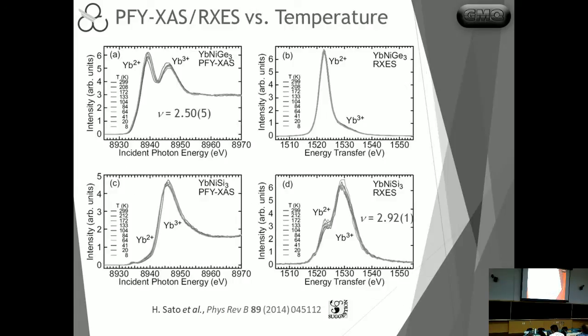An interesting thing, which I think was actually the first time that they could show this very well, was that for different systems you do get different types of responses. And so different techniques can be applied to different systems in order to get better resolution. You can see that the PFY measurement works very well for the ytterbium germanide. You can clearly resolve some very strong peaks here of 2+ and 3+, while the resonant emission spectra doesn't really resolve the 3+ aspect well. So this is not a good technique to study this compound.